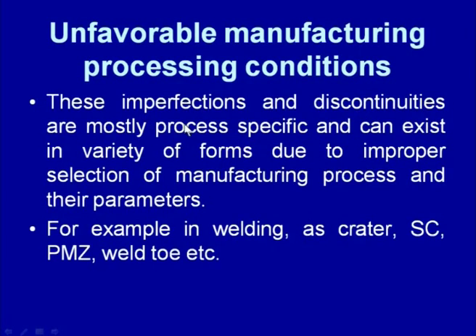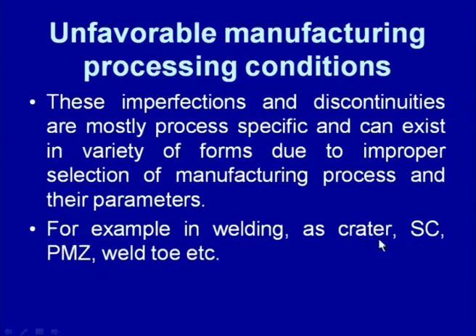These imperfections and discontinuities are mostly process specific and can exist in a variety of forms due to the improper selection of the manufacturing process and their parameters. For example, in welding, mostly you will find craters, solidification cracking, cracks in the partially melted zone or the weld toe. These are the typical features which are associated with welding only, while in case of castings we will find blowholes, porosity, piping defect, while in case of forged components there may be surface cracks, undesirable flow of the grains. So, many discontinuities and defects are process specific, and they form the basis for either stress concentration or for easy nucleation of the crack and the fracture of the component.